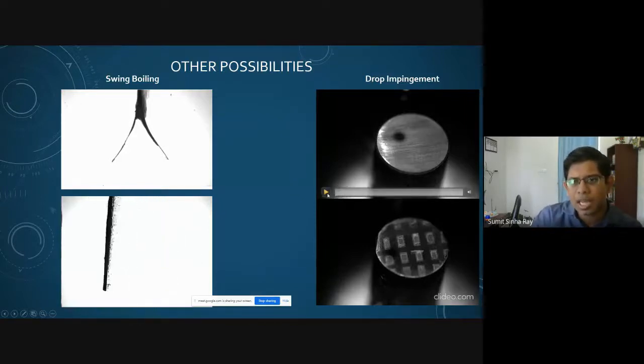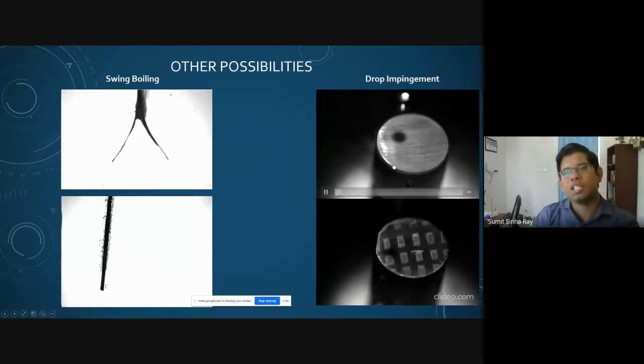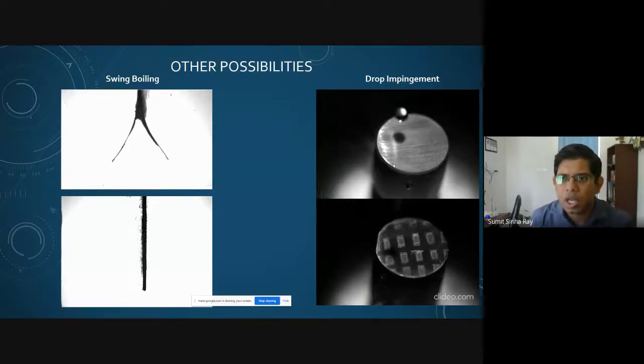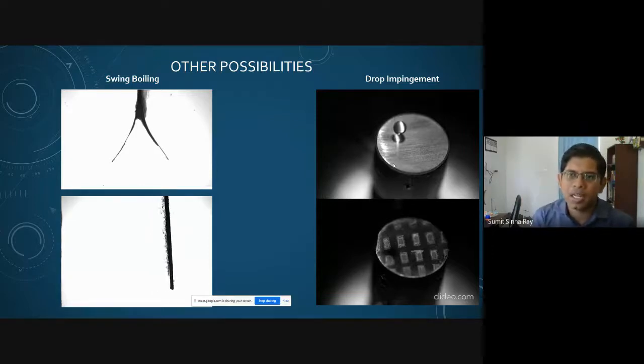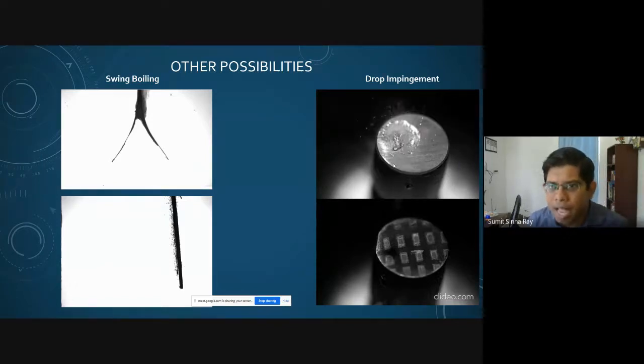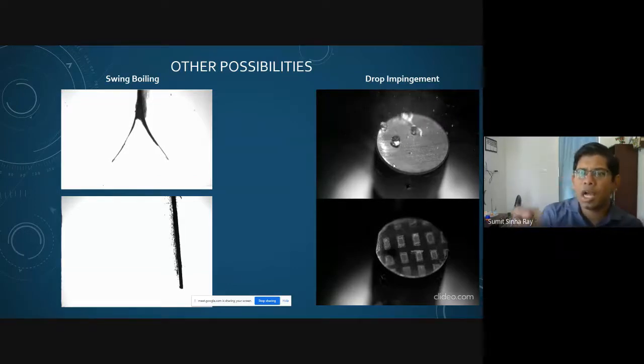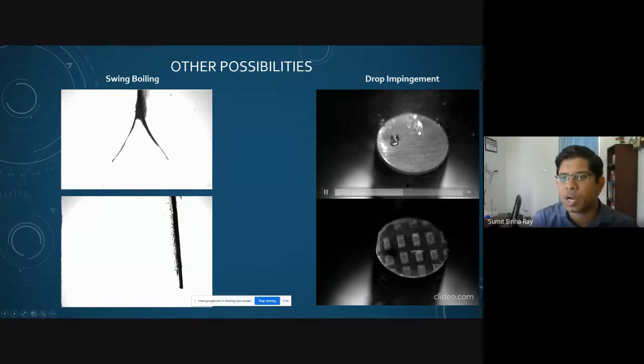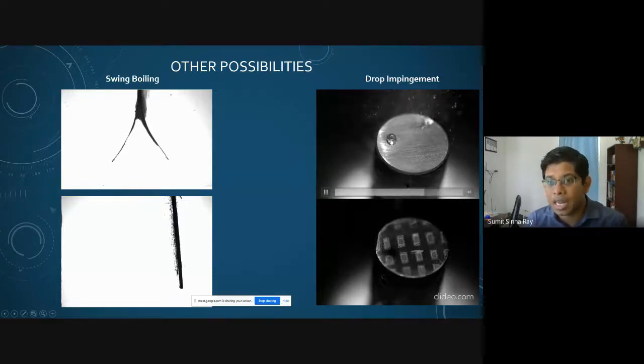Now, at the same time, if I show you this video, this high-speed imaging, this is a superheated substrate where an ethanol drop was hitting, and you can see that it spreads out, boils immediately, and then there is a lot of atomization happening. Eventually they form a couple of big droplets, and these droplets over here tend to run away from the surface, and this droplet stays as it is. It is not changing its volume at all, and it is trying to go towards the edge where it can leave.